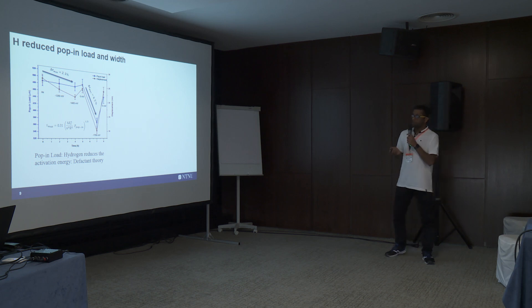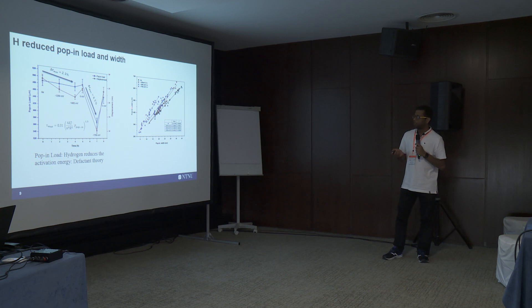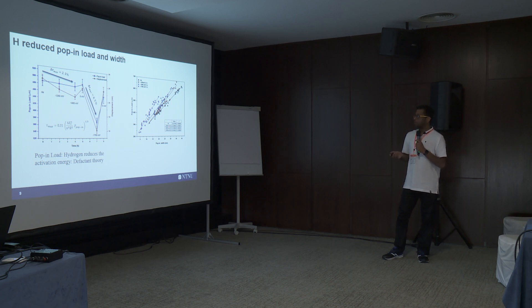Regarding the hydrogen-reduced pop-in width: I have plotted the pop-in load as a function of pop-in width, and the slope can be correlated to the hardening process. With hydrogen charging, there is an increase in slope, which suggests that increasing the hydrogen concentration increases the lattice friction stress.